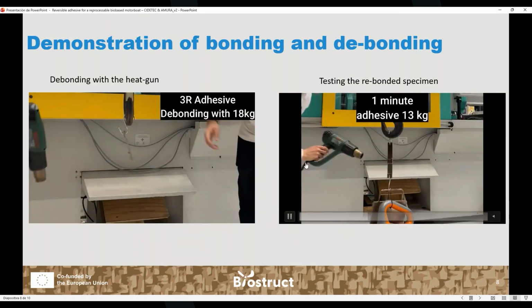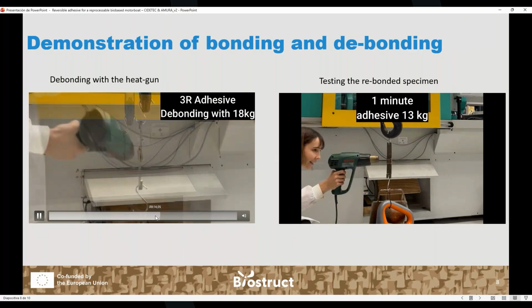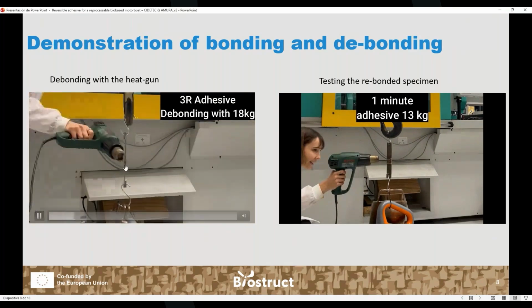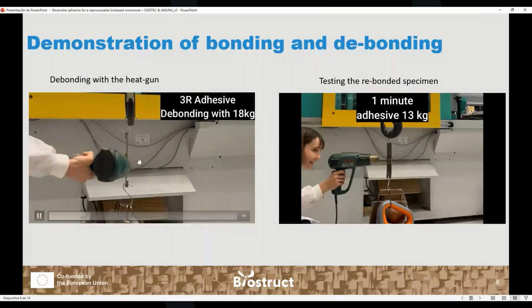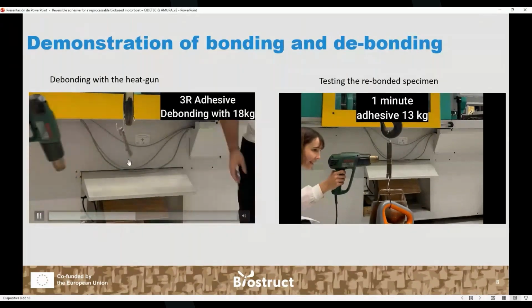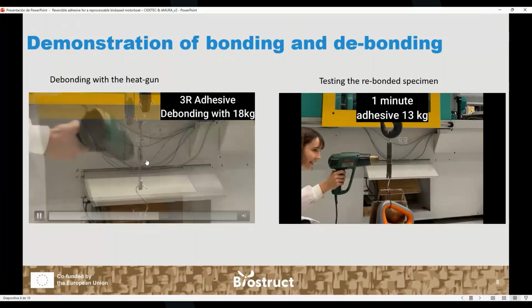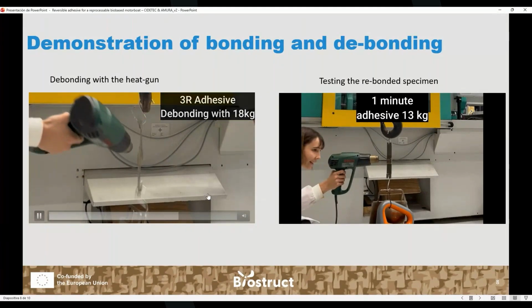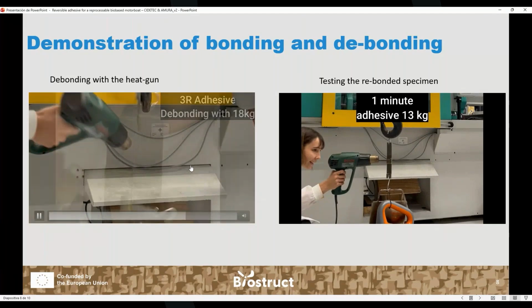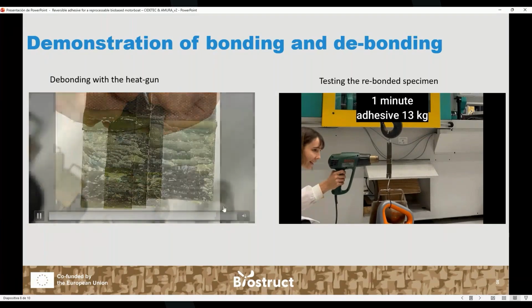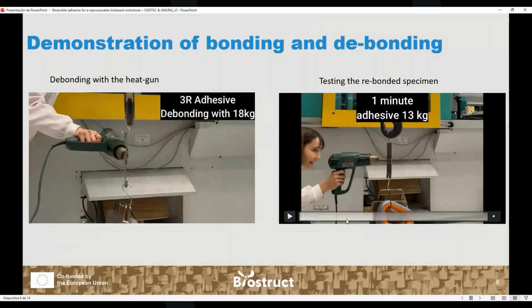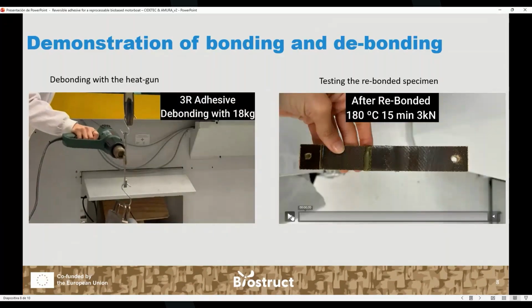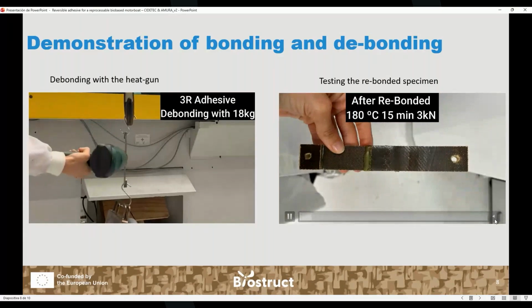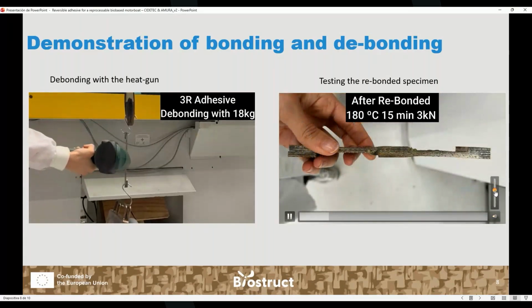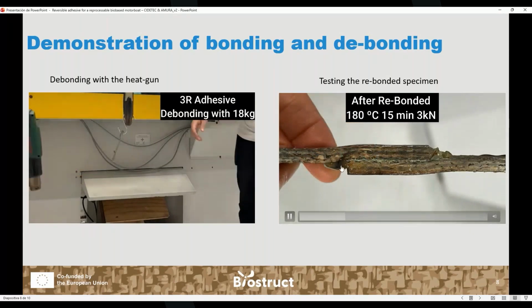In the first one, you can see that, maybe I will put it again. If we heat this specimen and we put some 18 kilograms, we heat the material and we can debond the material. And as you can see here, we obtain a more or less cohesive failure of the adhesive. So in the next video, you can see that we repaired this specimen by just applying heat and pressure here,